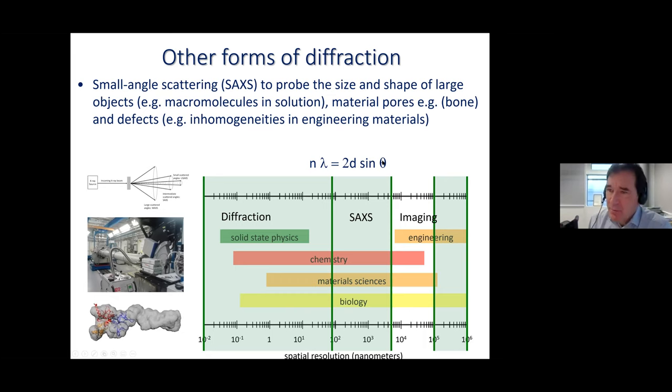So if we could measure diffraction down to hundredths of a degree, we would be able to measure, and if lambda is typically a wavelength that's of the order of the spacing between atoms, then we'd actually be able to measure objects that were hundreds of atoms across. And that's exactly what we do in small angle X-ray scattering. And I'll actually come back to this more with the neutron measurements, but it's really to say that by analyzing the scattering through these very small angles, you could measure large objects or you can measure defects and discontinuity in large objects.